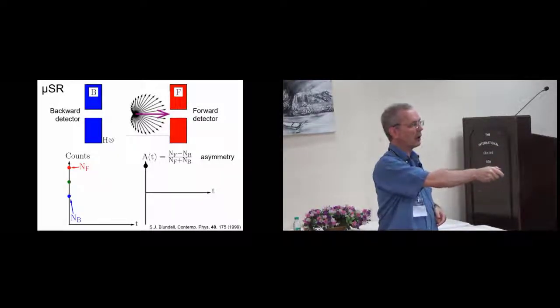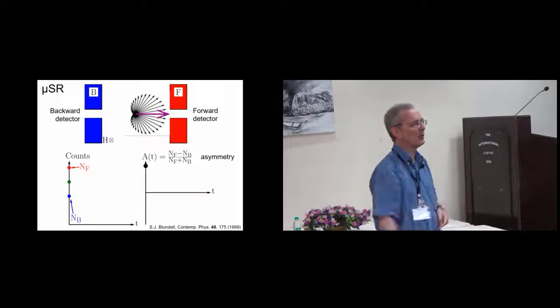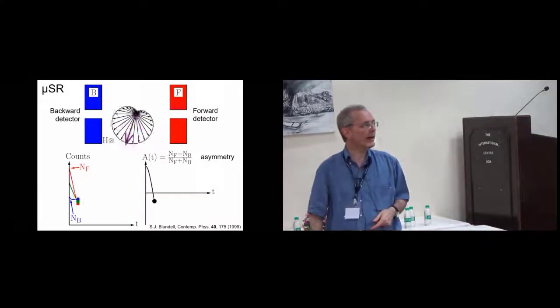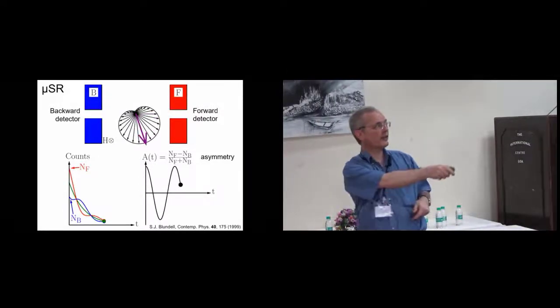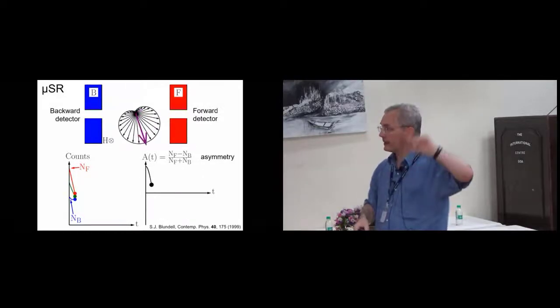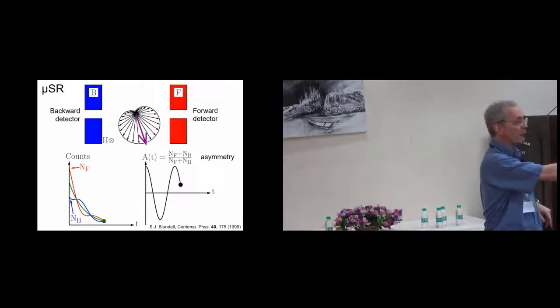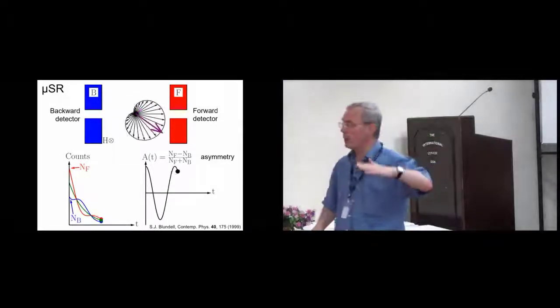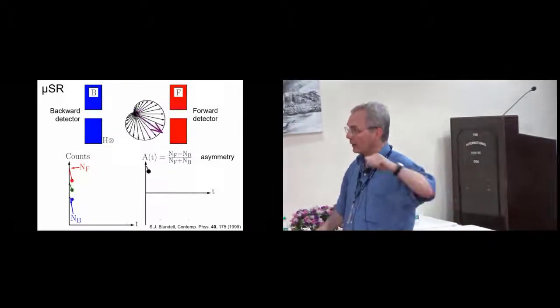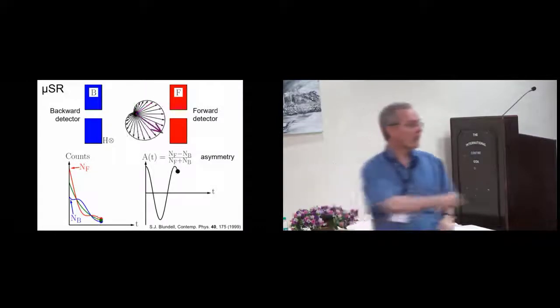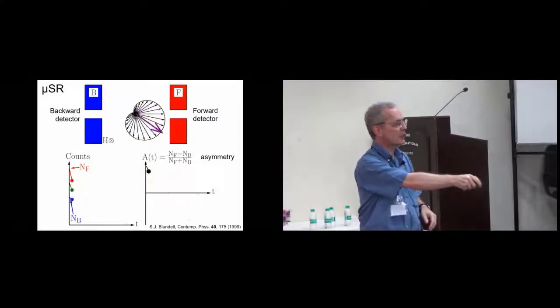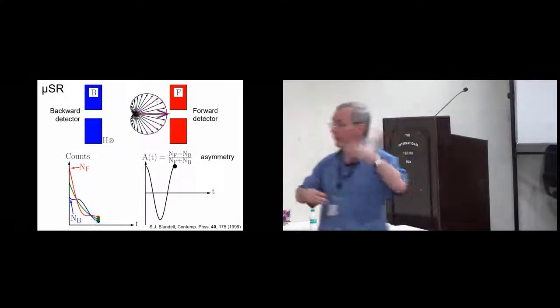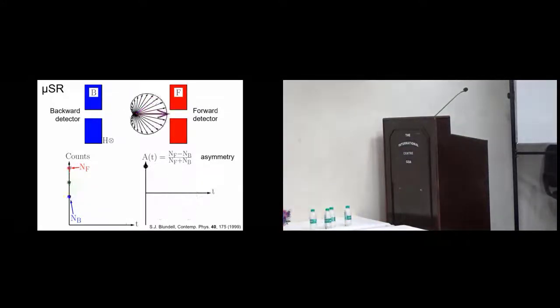And so if we plotted a graph of counts against time, here we are at time equals zero, we have more in the forward detector than in the backward detector. But now if we let time evolve, because of this magnetic field, the muon precesses. And what happens is, on average, that's this green curve, you just see radioactive decay. There are fewer muons lasting in your sample as time increases. But what you have is this oscillation about the green line of the forward counts and the backward counts.